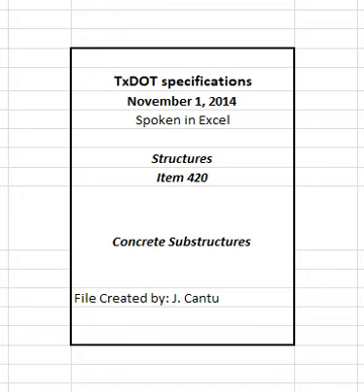On surfaces to receive a rub finish in accordance with Item 427, Surface Finishes for Concrete, chip out exposed parts of metal chairs to a depth of 1/2 inch and repair the surface. Remove all fins, rust staining, runs, drips, or mortar from surfaces that will be exposed. Smooth all form marks and chamfer edges by grinding or dry rubbing. Ensure all repairs are dense, well bonded, and properly cured. Finish exposed large repairs to blend with the surrounding concrete where a higher class of finish is not specified.